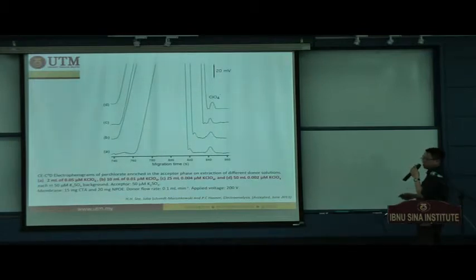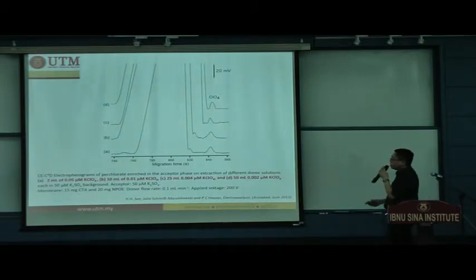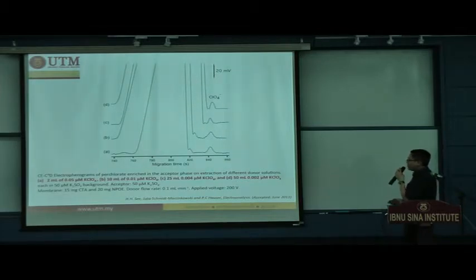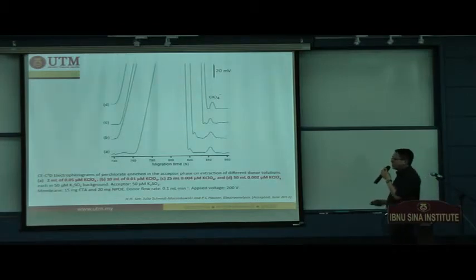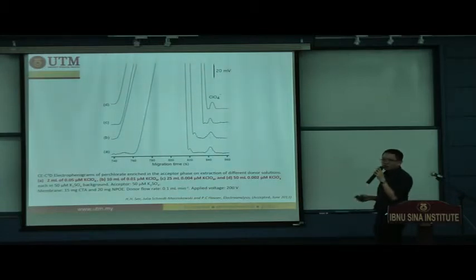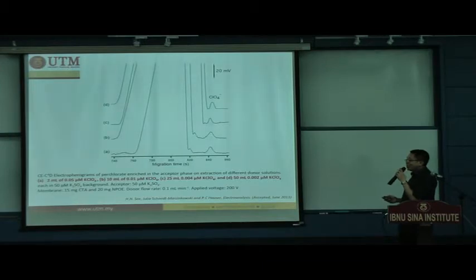Actually, similar peaks are observed, but when you look at the combinations, number A is 2 mL of sample with 0.05 micromolar of perchlorate present. But for number B it is 10 milliliters of sample, but now the amount of perchlorate is much lower, only 0.01. But it still resulted in similar sensitivity in the capillary electrophoresis, which means if you want to detect very trace amounts of perchlorate, you can simply increase the amount of sample that you inject into the donor phase extraction chamber. But at the same time, you also have to consider that if you're putting in more sample, it takes more time. So this has to be a compromise between the time and the detection limits.